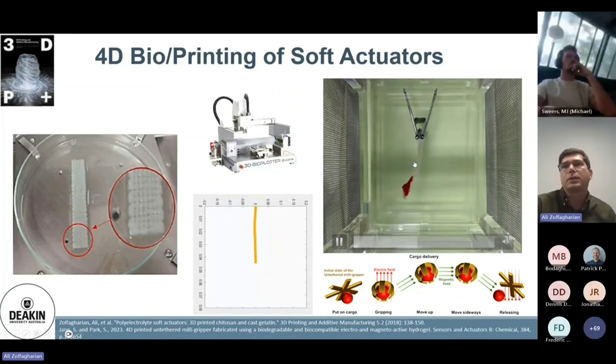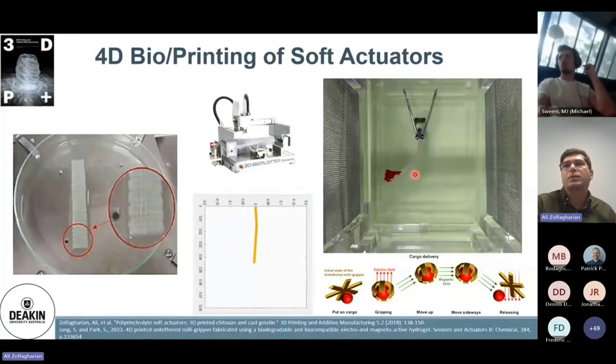We immersed the hydrogel into the electrolyte solution. We applied electricity on these electrodes, and based on the Donnan effects, the number of ions entering one side of the hydrogel was more than the other. Let me bring that pointer in, that might help better. The swelling occurs at one side of the hydrogel more than the other side due to the Donnan effects, leading to osmotic pressure buildup at one side that leads to some bending behavior. And it was reversible. With changing the polarity, we could get the reversible behavior.